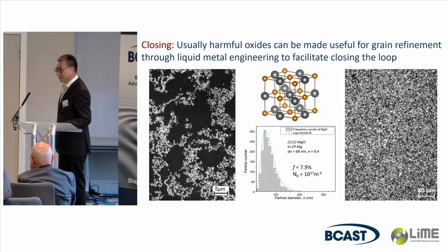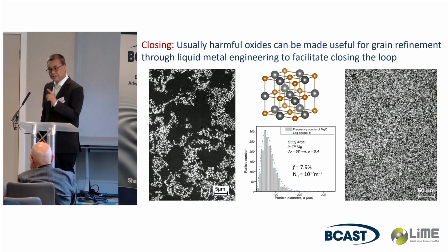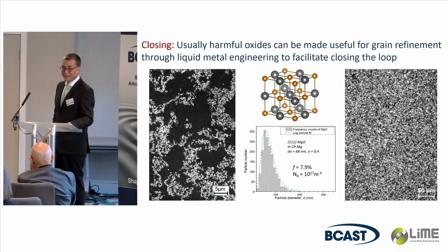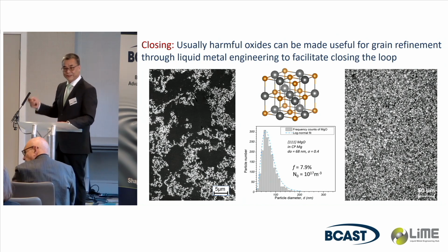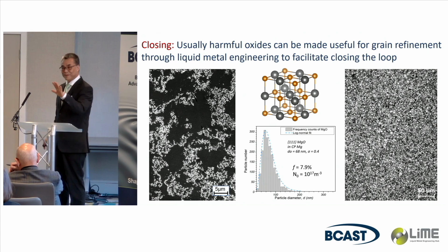And in the past 12 years or more, with LiME, we have been working on how we handle inclusions. And we found out, learning from nature, inclusion is quite a natural thing. You need to get rid of the harmful effect of inclusions, not the inclusion itself. But in the metallurgical industry, everybody uses filtering and all the purification processes in liquid metal to get rid of all this. And what we found out is that oxide, quite often, is not like solid pieces.